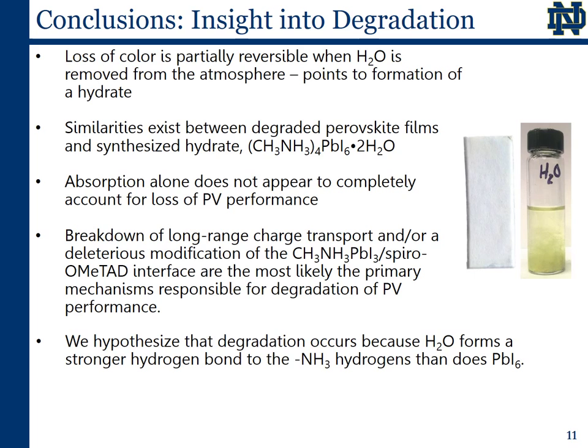In conclusion, we see a loss of color across the visible spectrum when perovskite films are exposed to humidity in the dark, which we attribute to a hydration of the methylammonium lead iodide. We see distinct similarities between this hydrate species and a previously characterized hydrate of methylammonium lead iodide, which can be formed from aqueous solutions of lead nitrate and methylammonium iodide.